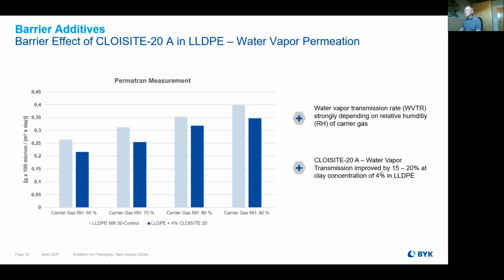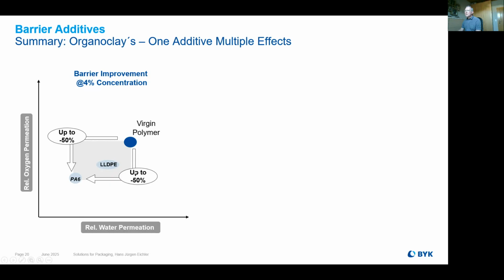So the clay is still doing a good job in case of the barrier properties, and that should be shown here in this figure. If we have, for example, the polyamide 6, you might be able to reduce the oxygen permeation by 50% and also the relative permeation for the water to 50%. With the LLDPE, it was with 4% concentration of the clay in the film, around 15 to 20%. So nice improvements, one way to have a chance of improving your barrier properties without different layer structures like it's classically done with an EVOH or a polyamide system in a tie layer system. So that's really interesting to follow.